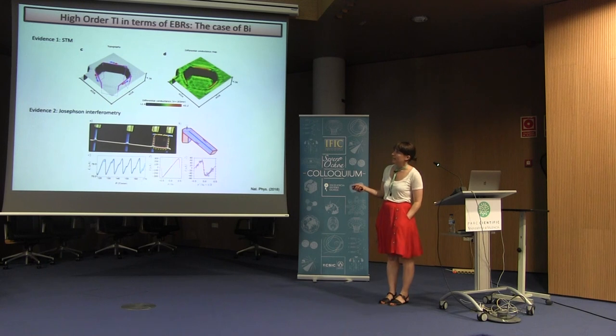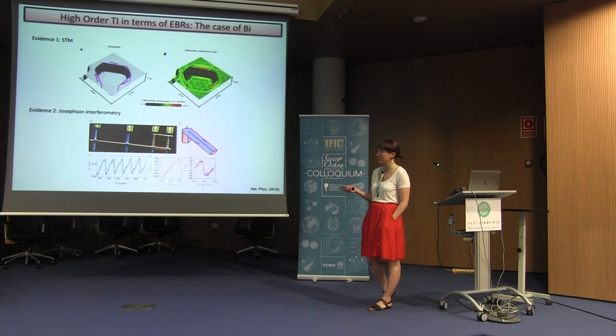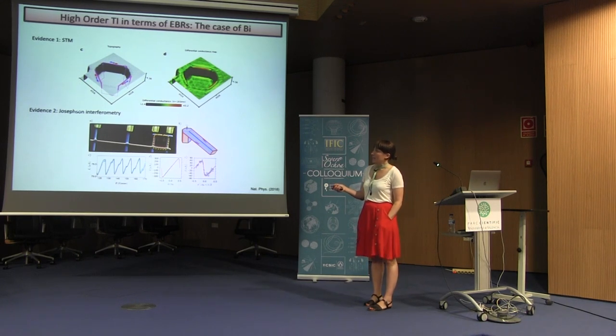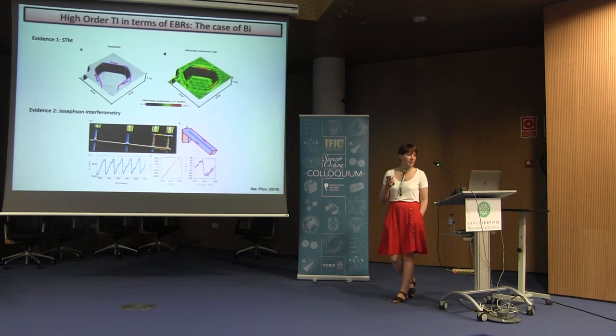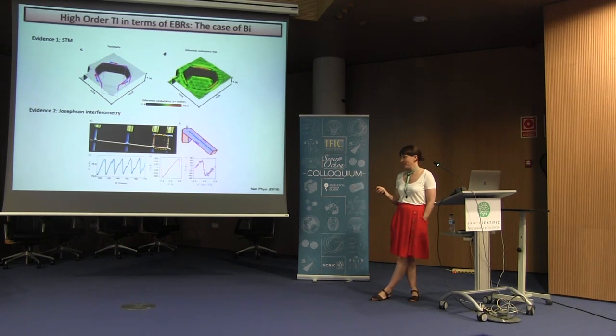So in the Yazdani group in Princeton, they measured this STM charge flow at the corners of a hole with hexagonal shape, which is actually what is predicted theoretically. And in Paris with the Josephson interferometry, they measured the difference of the critical current, and they also saw some quantization in the corners of a nanowire.